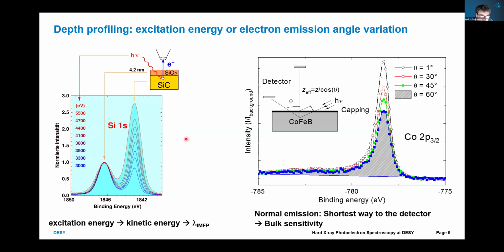As soon as we are bulk sensitive, we can, of course, benefit from non-destructive depth profiling of our samples, and you can do it basically in 2 ways. You can increase the excitation energy from, say, 3,000 up to 6,000 electron volts, and this is the standard example: natural silicon oxide on silicon. You see at 3000 eV excitation, the signal from the oxide is about the same as from the bulk, but when you increase the energy, then the signal from the bulk of the film dominates over the capping silicon oxide layer.